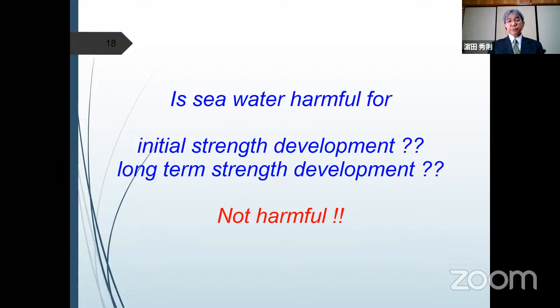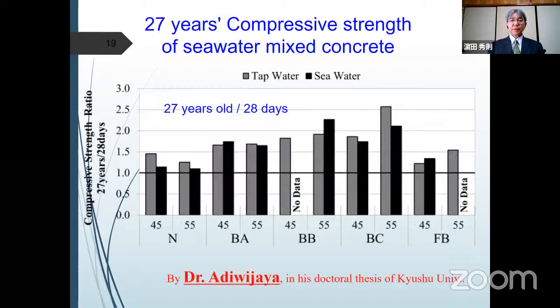So, is seawater harmful for initial strength development or long-term strength development? It is not harmful, no problem. This diagram is shown in the doctoral thesis by Dr. Adiwijaya of Kyushu University. It shows the strength change from 28 days up to 27 years with seawater-mixed concrete. You can see from this diagram, 27-year-old concrete shows 1.5 to 2.5 times the strength level of the initial strength at 28 days. So concrete strength is not affected by mixing seawater for the long term. 27 years after, it is no problem.